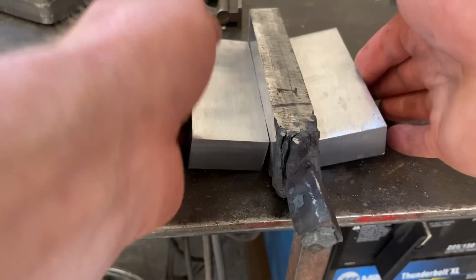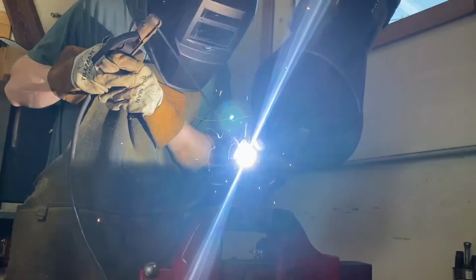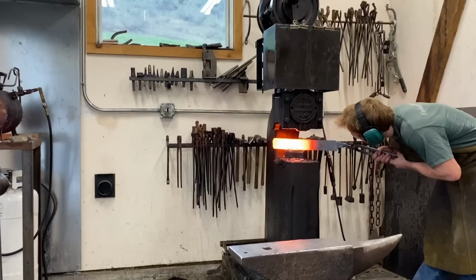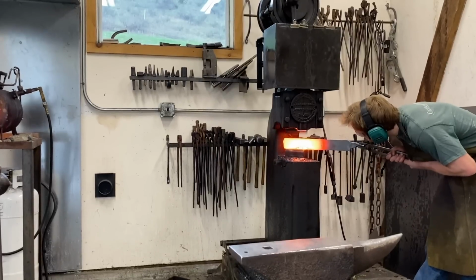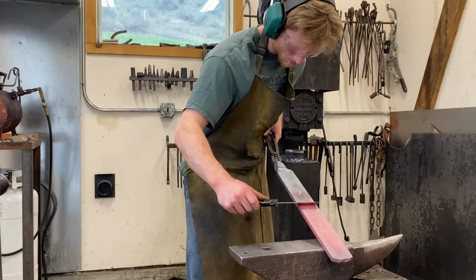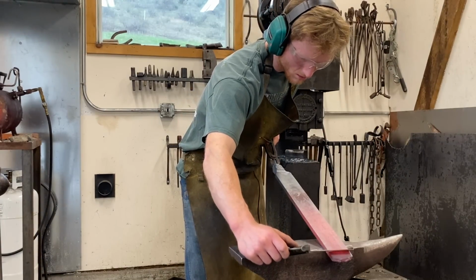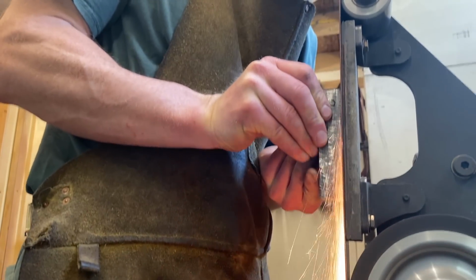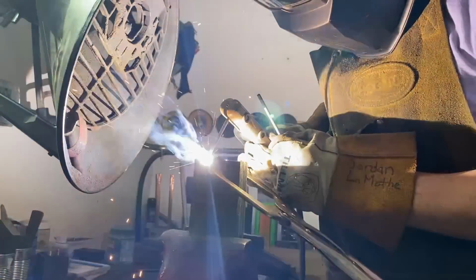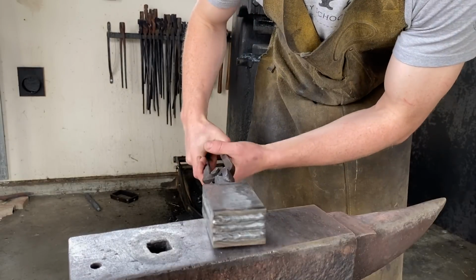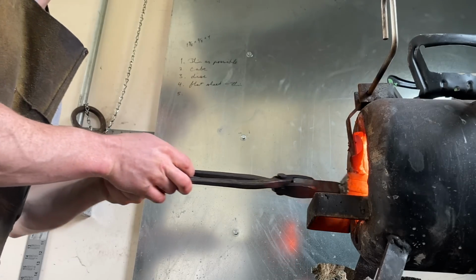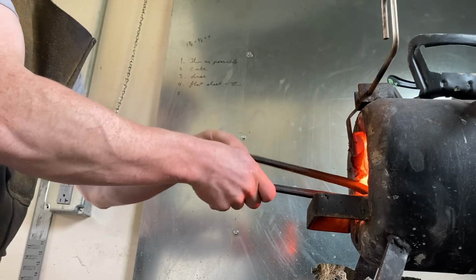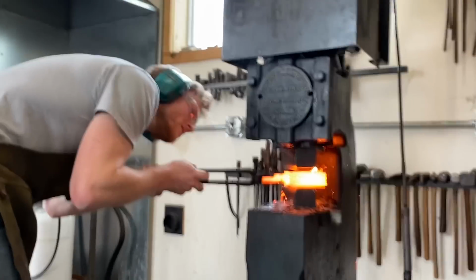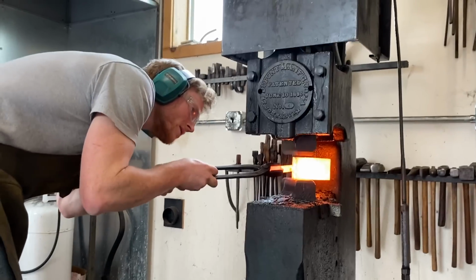The blade for this vegetable cleaver will be forged from damascus steel of around 388 layers of 80CrV2 and 15N20 high carbon steels. I clean and stack the metal, tack it together with a stick welder, then heat it in the forge, and when it's hot I can fuse it with the power hammer and draw it out to length. I repeat this process at least 5 times to achieve the desired number of layers.